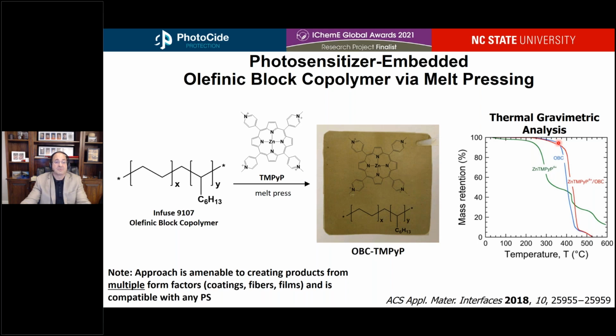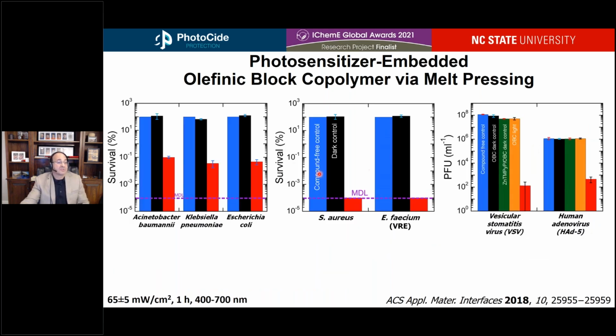The material turns out to be highly antimicrobial against gram-negative pathogens, shown here on the left-hand panel. We have inactivation ranging from 99.9 to 99.96% against these gram-negative pathogens, 2 of which are drug-resistant strains. Against the middle panel pathogens, which are gram-positive pathogens, essentially 100% inactivation to our minimum detection limit, including drug-susceptible and drug-resistant strains.